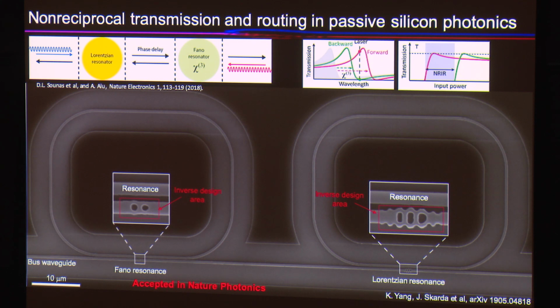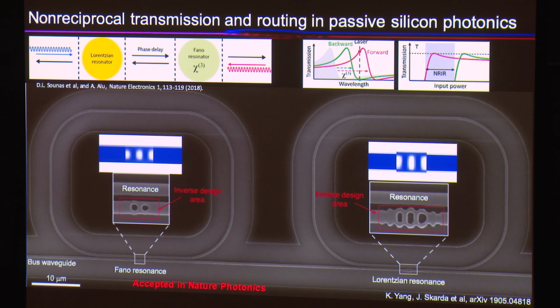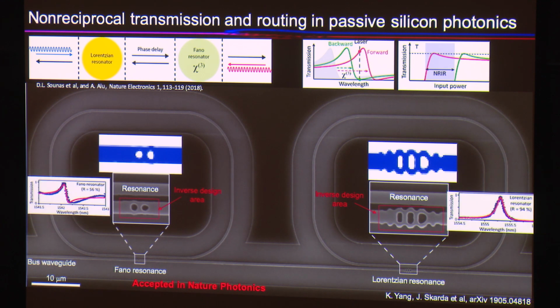So we just started from 2 resonators coupled to a waveguide. And then we let our optimization software control the coupling region between these resonators and waveguides to achieve here Lorentzian transmission on the right, and here to achieve Fano transmission that we desire. And here you see the optimization process. This is a pretty small structure. Something like this would take less than an hour for sure, because it's a pretty small region you're optimizing. And then when you finish and measure transmission, it matches your design behavior, and here as well.